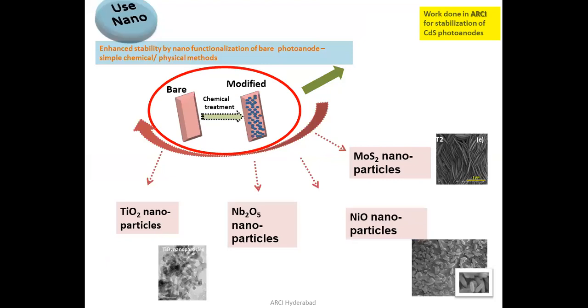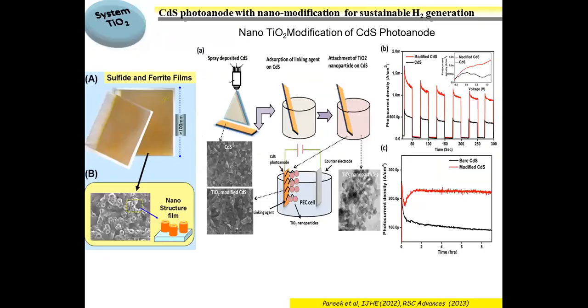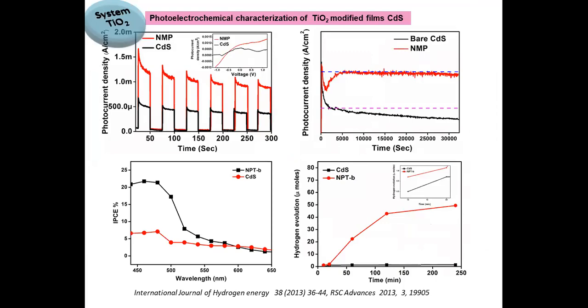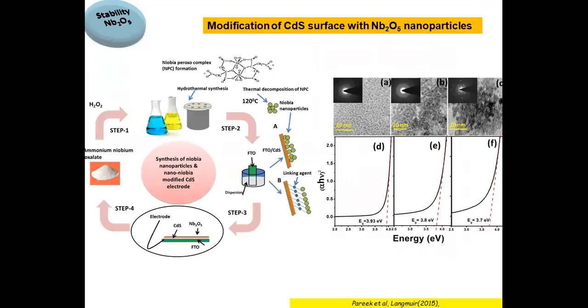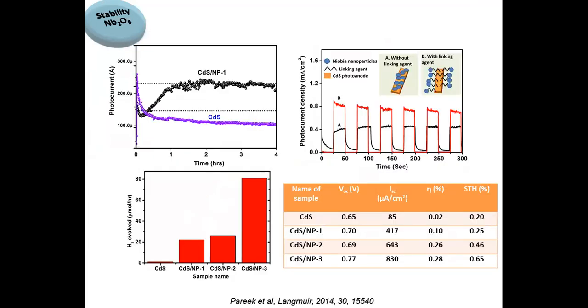So we tried nano systems of TiO2, niobate systems, MoS2 nanoparticles, and nickel oxide nanoparticles for functionalization of CdS-based photoelectrodes. It was very interesting to see that nano TiO2-based functionalization gave us very suitable, stable and sustainable hydrogen generation. So this is the important outcome. How has this happened? Just by our basic understanding and materials science engineering. The second system, niobium oxide, we tried, and that is what we can see in the stability. It has also shown very good stability.